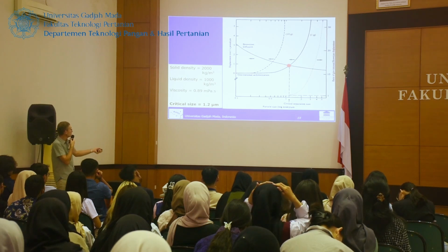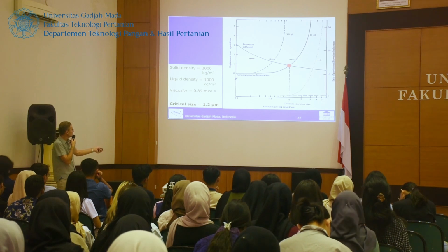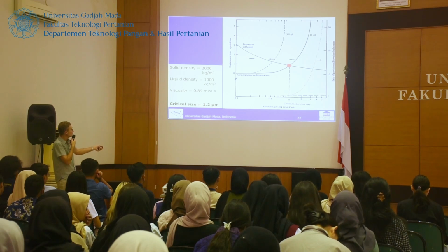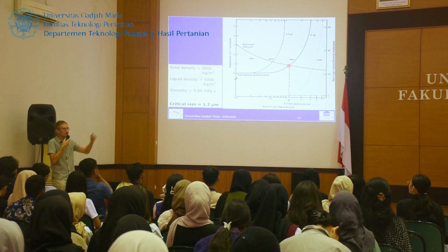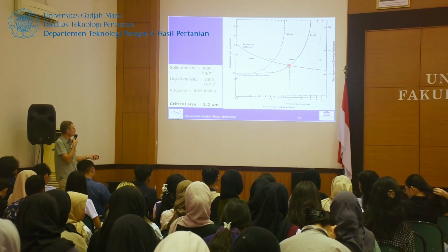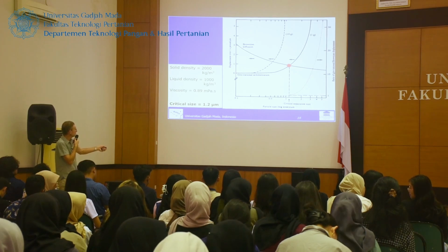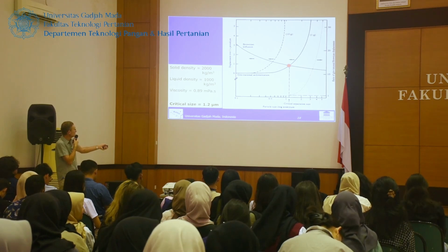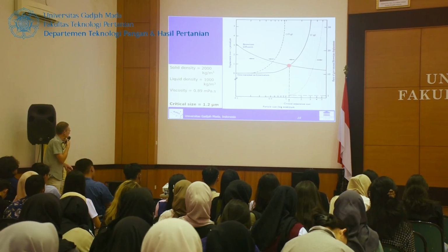And then indeed, you see that you come to that range of about 1 micrometer. That says for smaller particles, the Brownian motion is more important than gravity. So that means that your dispersion remains homogeneous, that your particles move especially in random directions and not just going in one single direction to the bottom or to the top. Whereas if you have bigger particles, above that critical region of about 1 micrometer, then your particles mainly will be subjected to the gravity effect, because their Brownian motion becomes less important.